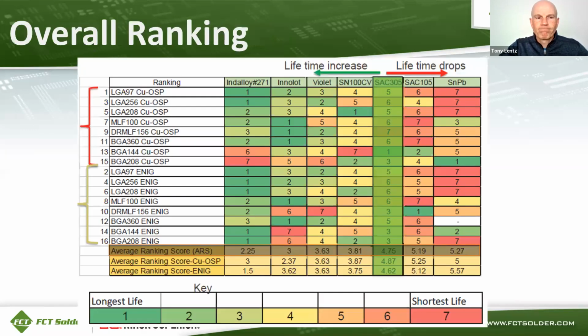So here's an overall ranking that was summarized in this work. What you have in the first column are the different components that were used, and then the different surface finishes, copper OSP and ENIG. And then in the very center, the green highlighted column is SAC305 for reference. So the scoring key on this is anything with a 1 or a 2, or the green highlighted cells, are the longest life or the best performing combinations. And then the red colored cells are the worst performing combinations with scores of 6 or 7 in them.